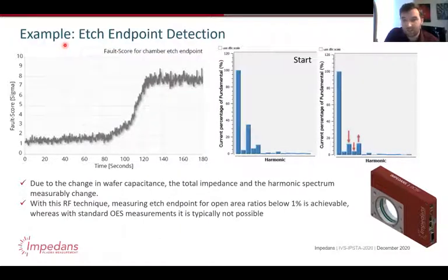So I'm going to give you an example of these sort of changes and how easy they are to see. This is taking all the harmonic data and impedance data from one of these sensors, and we're monitoring etching. As you go from one layer to another in a process, you want to make sure that you can stop at the right time, so you don't over etch, or you don't go through too many layers, or you stop at the right distance in the layer. That's called endpoint detection. You tell the plasma when to stop the process.